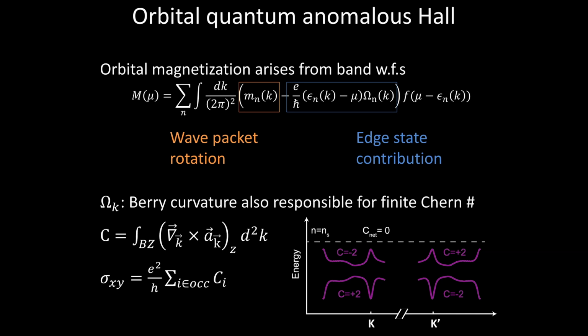So if you change the occupation of this edge state, actually that's a very large diameter current. So it's a pretty large effect. It's a pretty large orbital magnetization. Interesting. So one of the experiments we wanted to do was to try to understand quantitatively, first of all, is this indeed an orbital magnet?